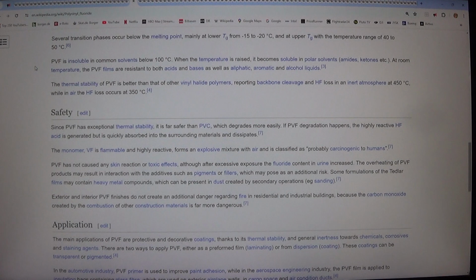PVF is insoluble in common solvents below 100 degrees Celsius. When the temperature is raised, it becomes soluble in polar solvents, amides, ketones, etc. At room temperature, the PVF films are resistant to both acids and bases as well as aliphatic, aromatic and alcohol liquids. The thermal stability of PVF is better than that of other vinyl halide polymers, reporting backbone cleavage and HF loss in an inert atmosphere at 450 degrees Celsius, while in air the HF loss occurs at 350 degrees Celsius.